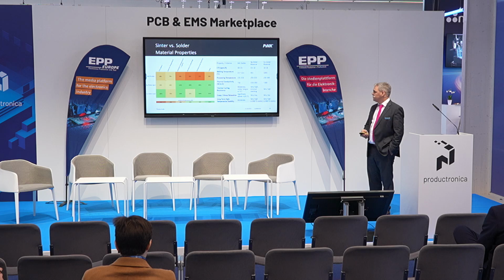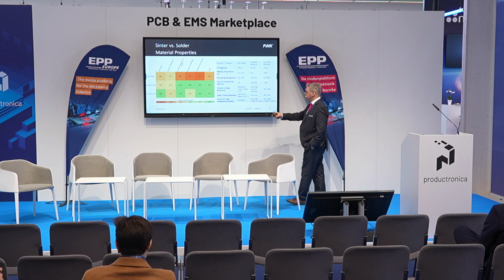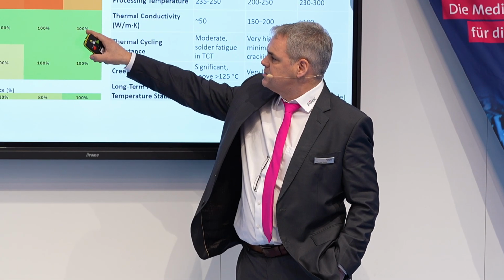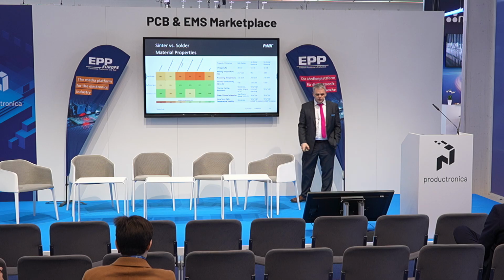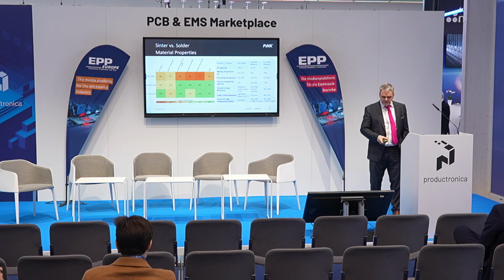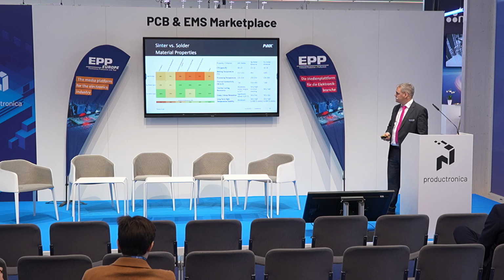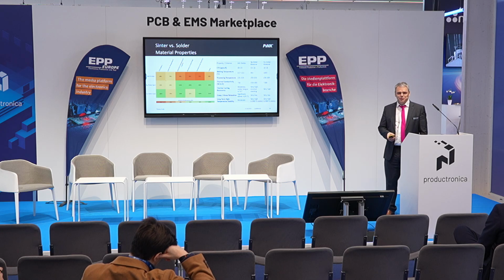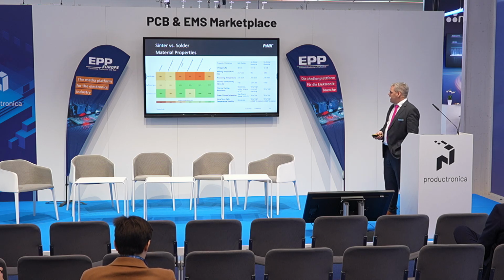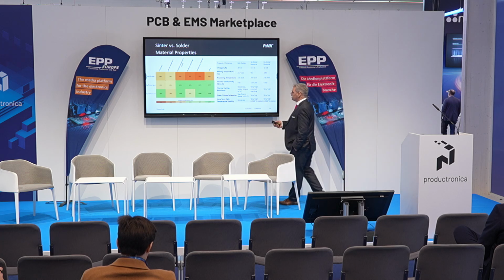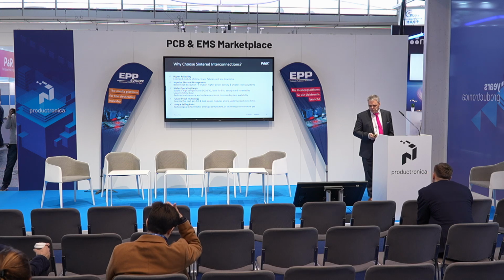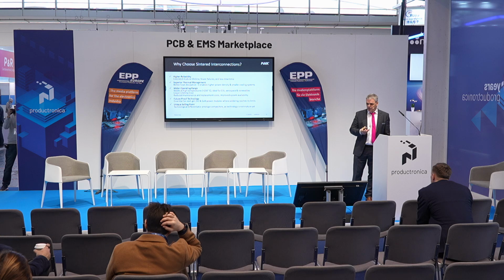I tried to do something quite similar. I tried to compare the different materials. In the upper line I used SAC solder, here I used silver sinter, and here I used copper sinter. I looked at different material properties, like the CTE, the process temperature, the usability at higher temperature, and so on. Red means it does not fit so well, and green means it fits well. What we can see is a lot of green for silver sinter, but also for copper sintering. So in terms of compatibility to copper sintering, the silver sinter layer or the copper sinter layer would technically be of benefit.